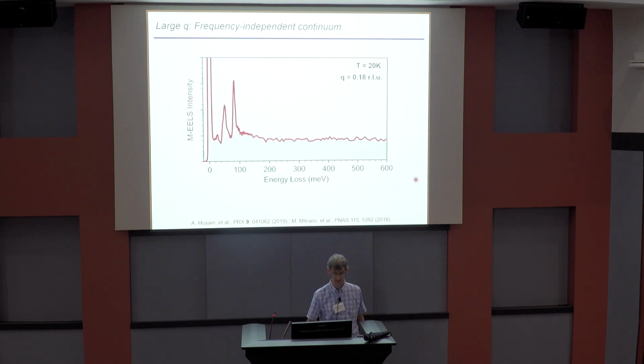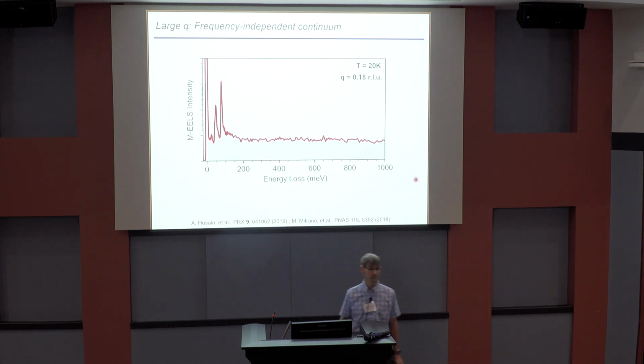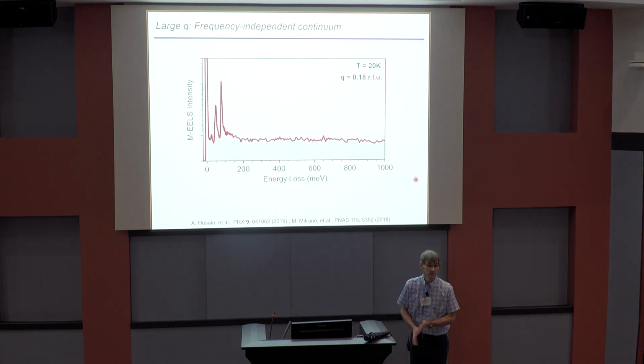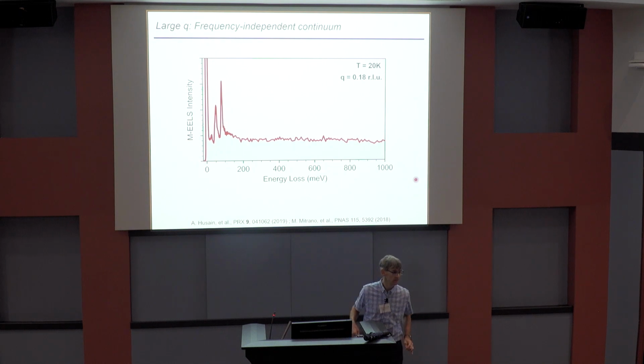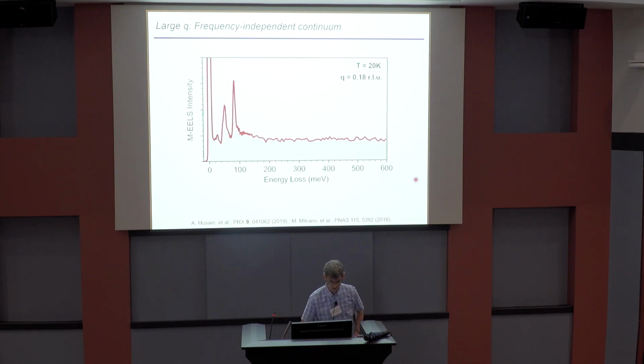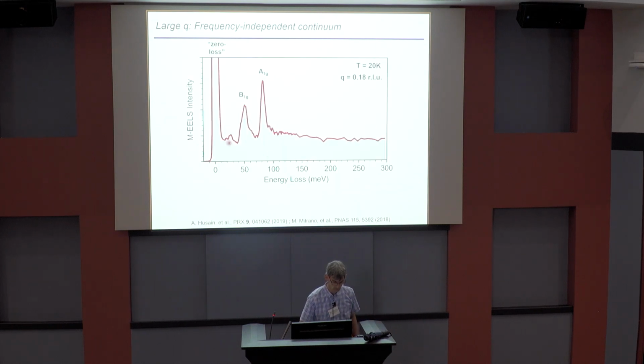But you can keep scanning. If you go up to 600 meV, it's still more or less constant. You can go up to an eV and it's still there. So the way you establish the background is from the energy gain side. Actually, on the energy gain side you can see the background level, right? So that's 0. So this is real excitations, and it's very strong.